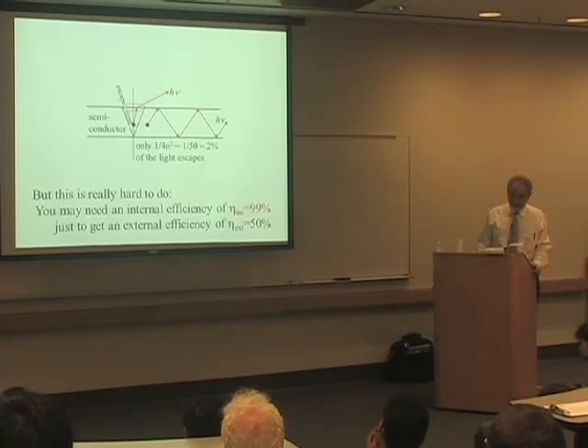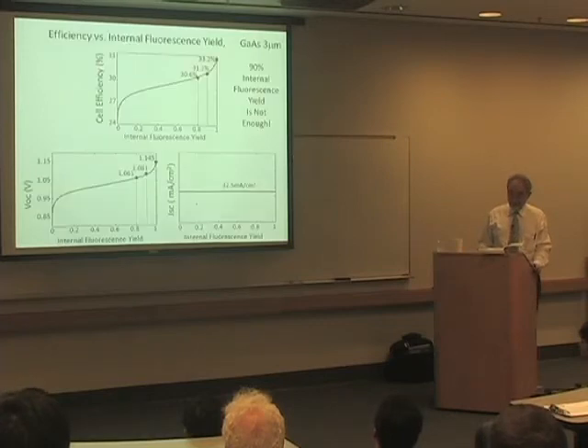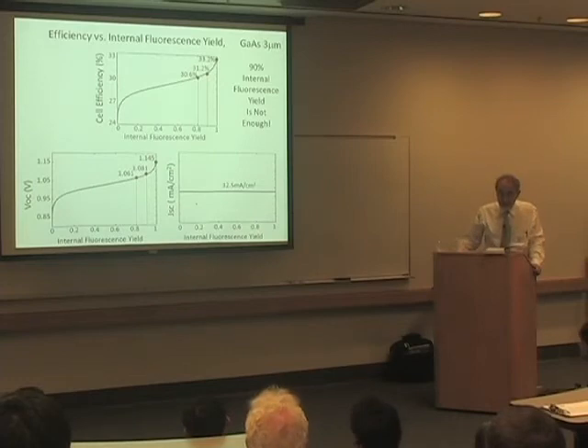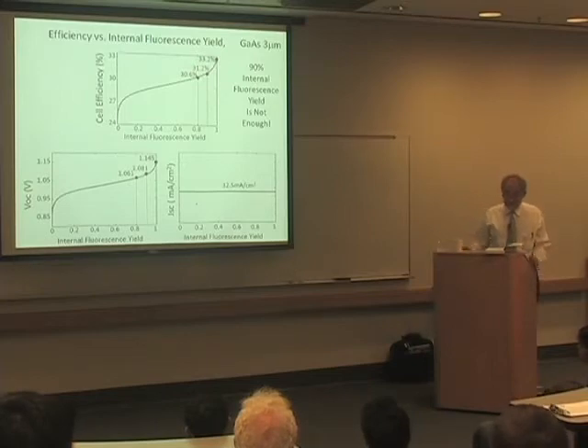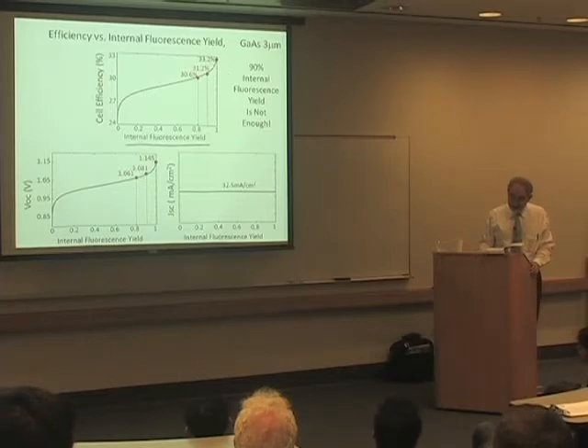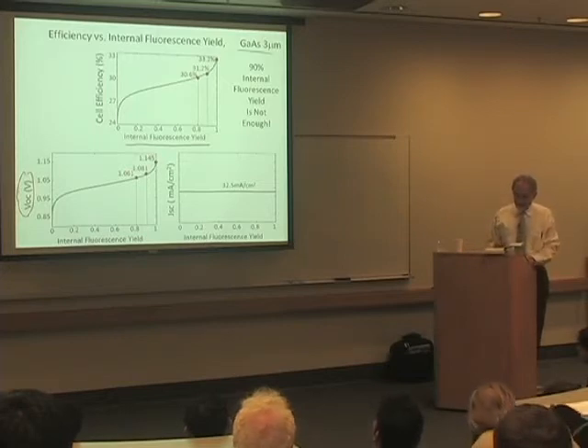But it's really hard to do this because you do need this phenomenal internal fluorescence yield just to get a moderate external fluorescence yield. So let me show this to you based on calculations of how important it is to go well beyond 90% internal fluorescence yield. So this is the internal fluorescence yield versus the cell efficiency and also the open circuit voltage. Let's look at the open circuit voltage. And this, by the way, was worked out for gallium arsenide, but it's similar for other high efficiency materials.